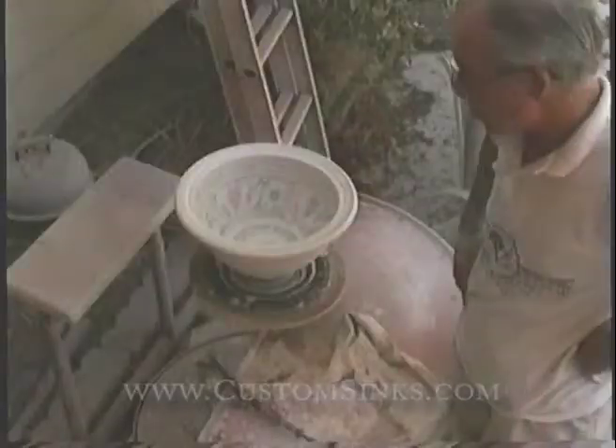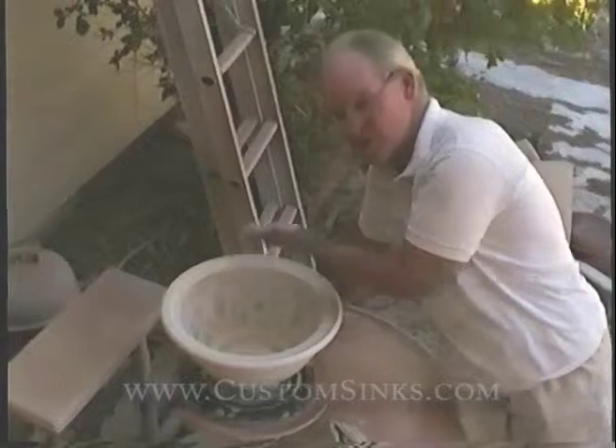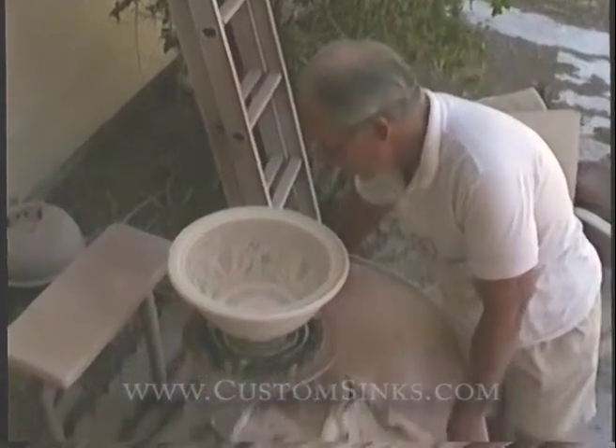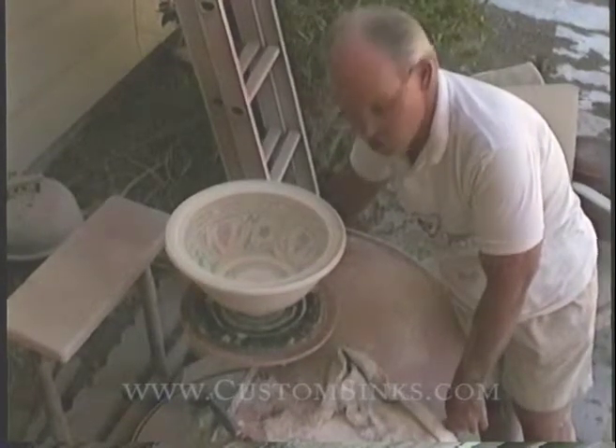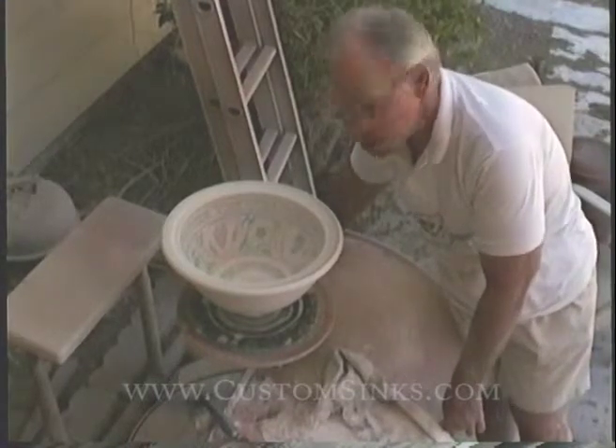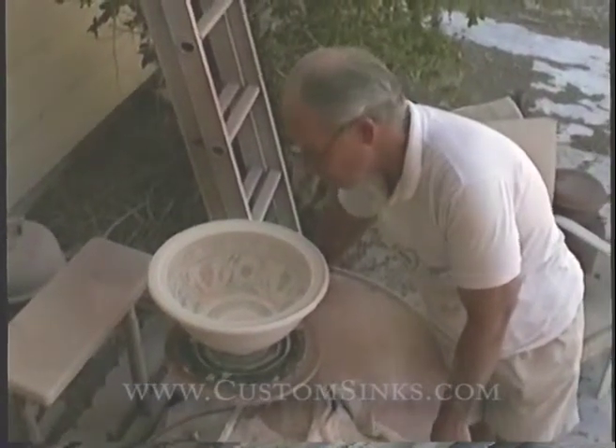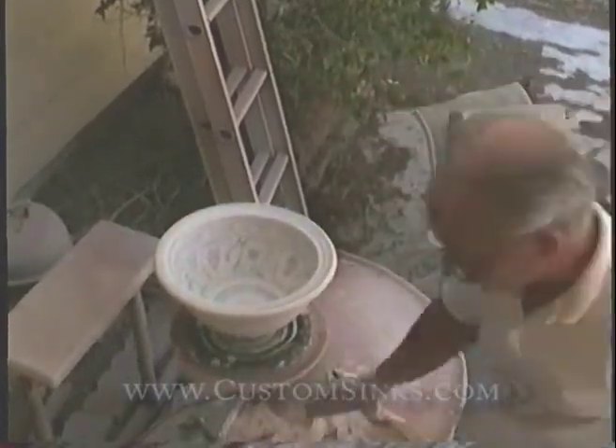All right, we're ready to glaze this sink, and we're going to cover these oxides up. The glaze we're going to use is called Cornwall Clear. It's out of College of the Redwoods in Fort Bragg. Bob Zielinski's glaze, and it's just a simple clear. It used Cornwall stone as its main ingredient, so it has kind of a green tinge. That's not really a color, that's in the feldspar. It's a cone 10 glaze, actually fires from about cone 9 to about cone 11. It's a nice variety, and it covers real nice. So that's what we're going to do. So here we go.